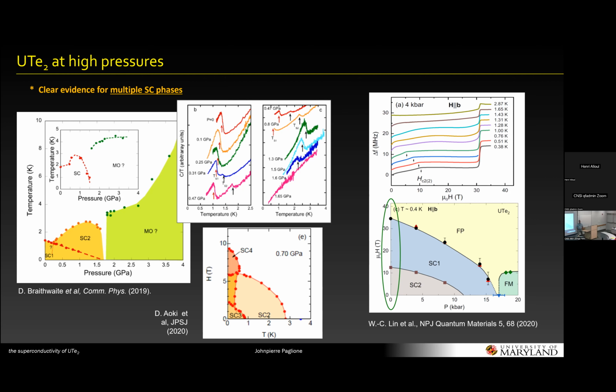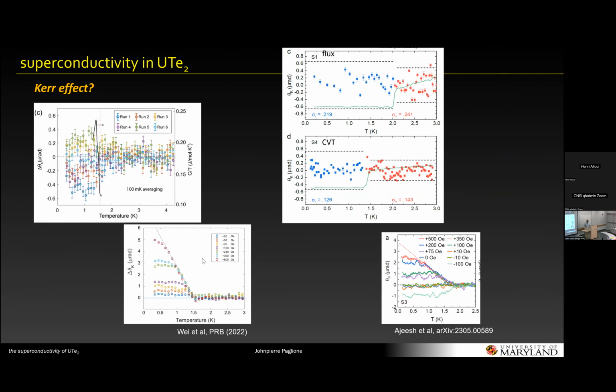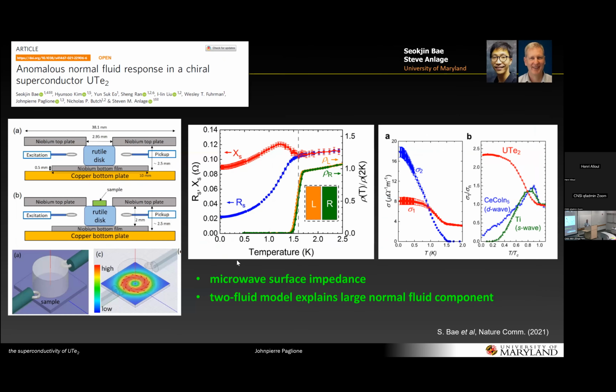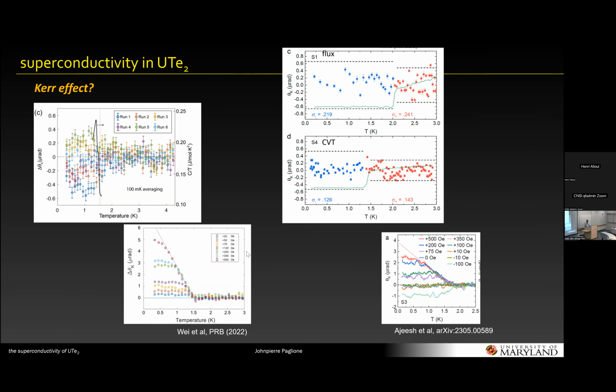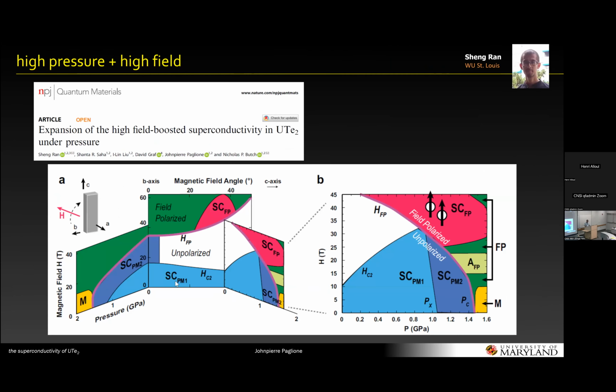Yeah, okay, Stuart. So, along the B-axis, you showed the nice data showing the reentrant type behavior. My question is on the low field part of that, the low field phase. Is it thought that the destruction of superconductivity, since you're adopting this triplet picture, is vortex physics for all that low field phase? I see. So anything that occurs higher has to be a completely new state then, because you're not killing. Yeah, I mean, my zeroth order response is yes, vortex physics, but the Hc2 anisotropy also follows the magnetization to some degree. So maybe something more complicated, but okay, I see. Good.